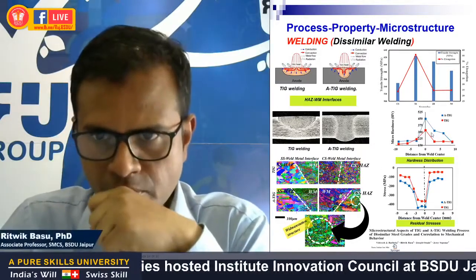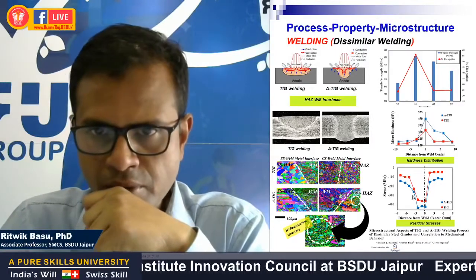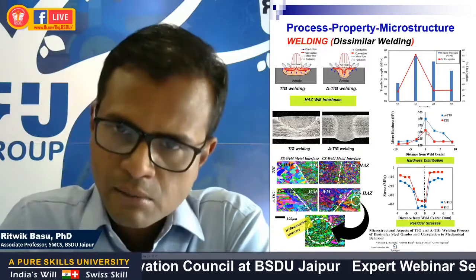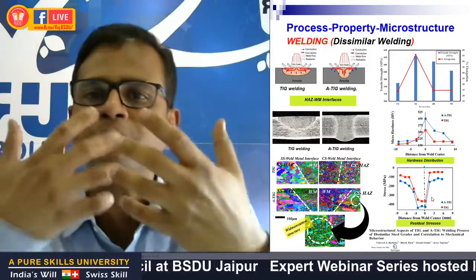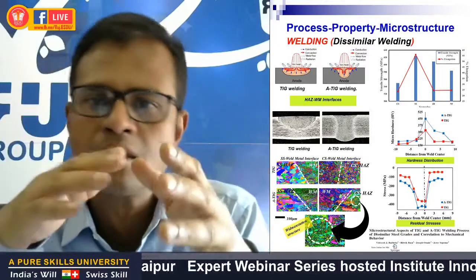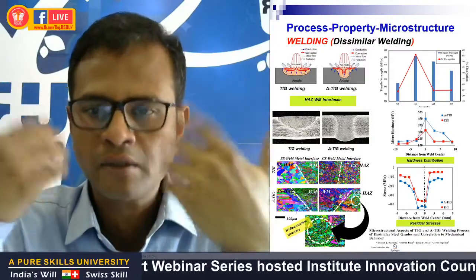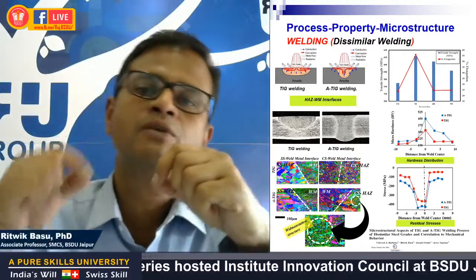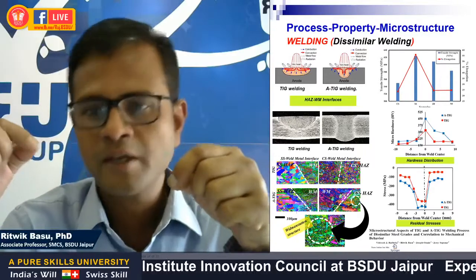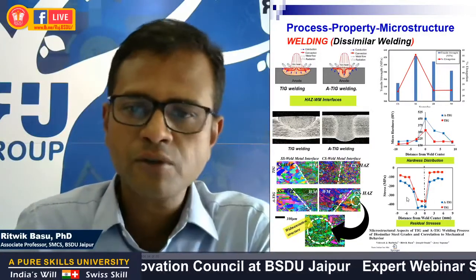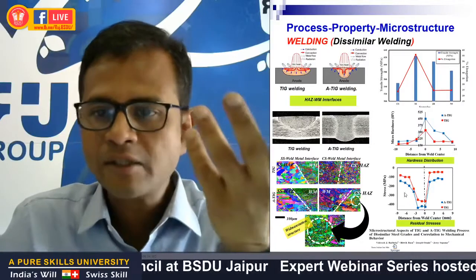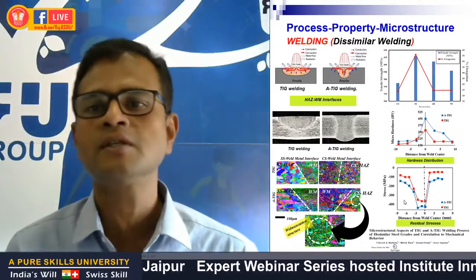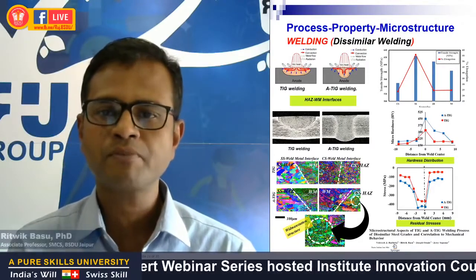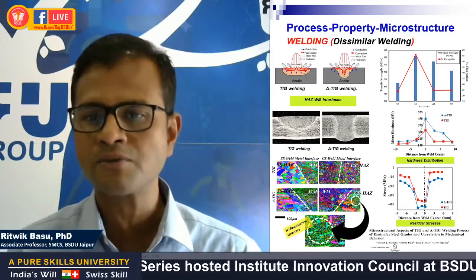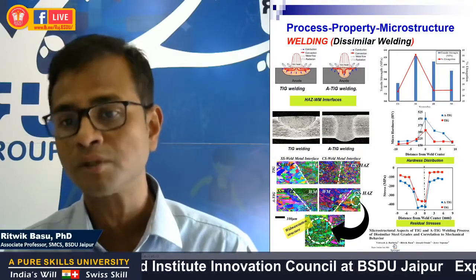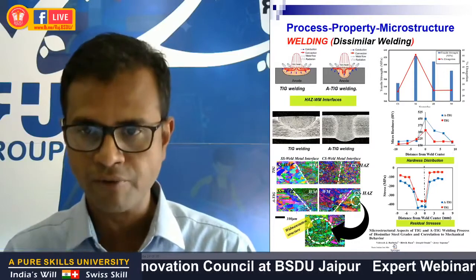Also, the measured hardness profile and the residual stress bring out some interesting observations. Although it is known that the maxima in the hardness corresponds to the minima of the compressive residual stress, with our samples, we did not see a direct correlation between the hardness and the compressive residual stress. So the residual stress that was measured along the weld surface exhibited a well-like profile, slightly shifted on the stainless steel side. Again, why this shift occurs is not clearly understood, but what is speculative is that the thermal mismatch strains between the stainless steel side, which had an FCC structure, and the weldment, which had a BCC structure, could possibly be responsible for the shift in the well-like profile.